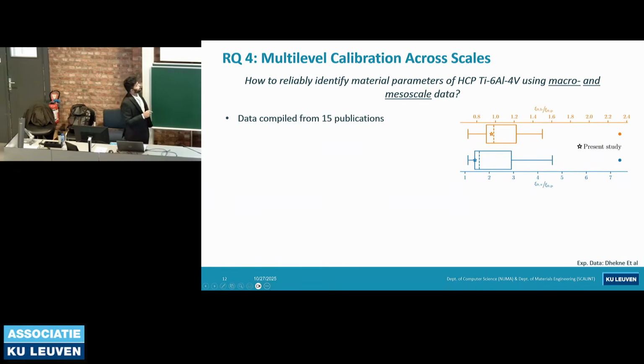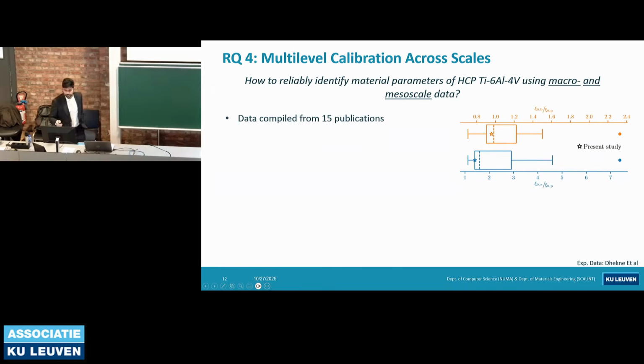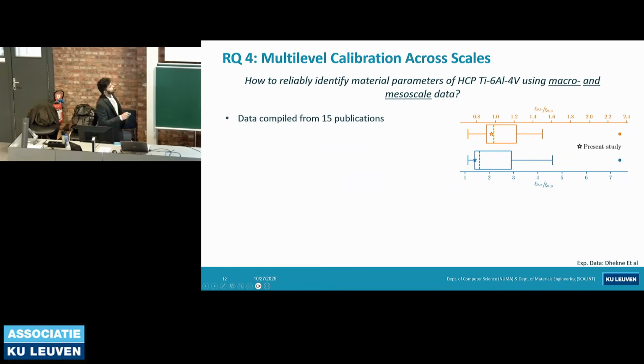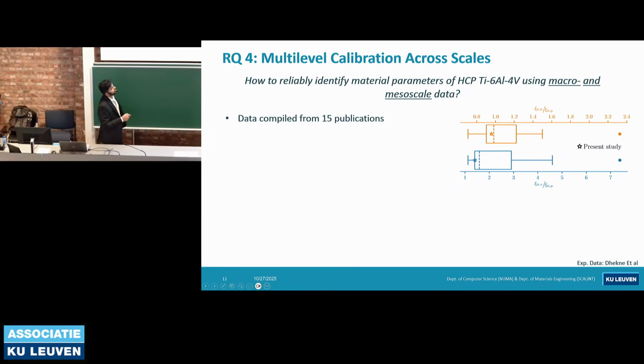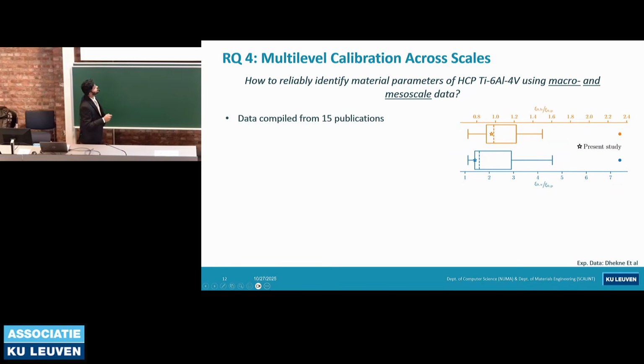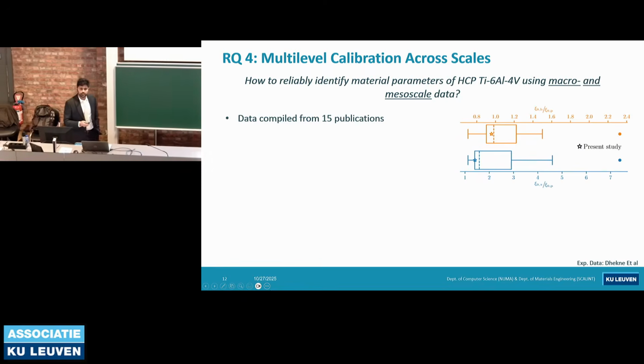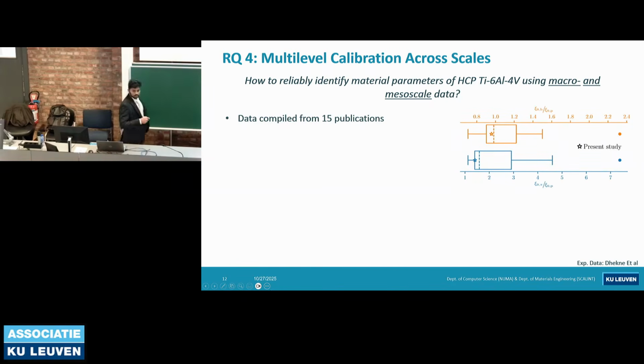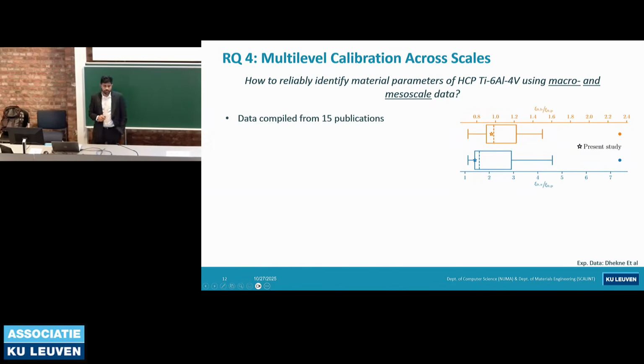So I've compiled these two parameters, ratios of CRSS. First, let's focus on this orange line, which is the CRSS of basal by CRSS of prismatic. And here, this is a box plot. So 50% of the values ever reported in these 15 publications are within this range. It ranges from 0.9 to 1.2. This doesn't seem to be that bad, right? But here, even a decimal point has a significant influence on the material behavior.